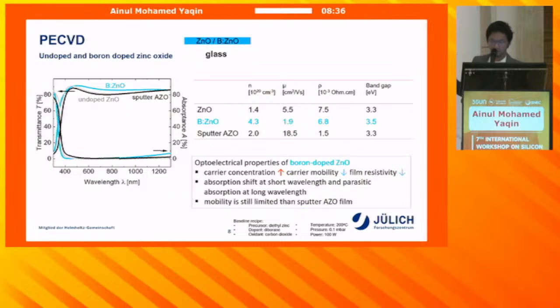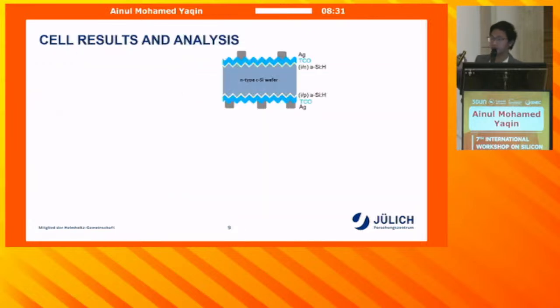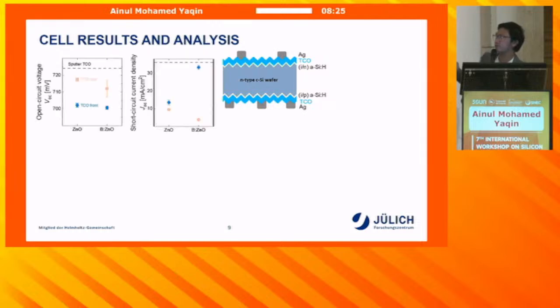So we are done with the development of thin films. We applied them directly to our solar cells, either on the front side or on the rear side. Here we have the undoped and boron-doped zinc oxide, and the dashed line corresponds to the sputter reference. At the moment, if we look at the VOC and the JSC, there's still a gap between our PECVD TCO and the sputter TCO.